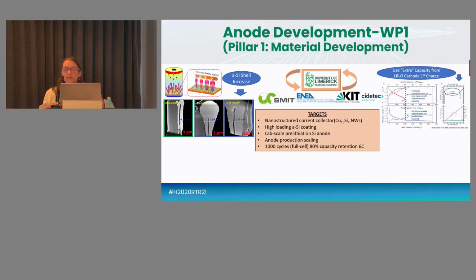As we all know, silicon has the drawback of a very high loss of the initial capacity, so we are working in collaboration with KIT on using the extra capacity coming from the lithium-rich cathode to compensate this capacity loss. Unfortunately, I don't have the graph of the very last result, but at the moment we achieve about 350 cycles with capacity retention above 90% with these strategies.